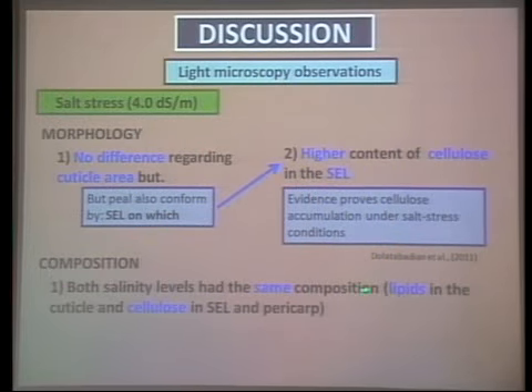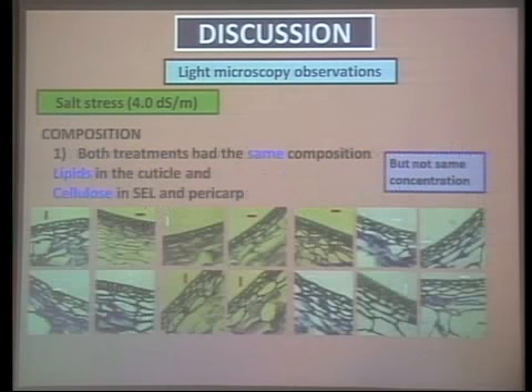In the morphology that we saw with light microscopy, we didn't see any differences in the cuticle area. But again, the peel is not just the cuticle. It's also the subepidermal layer. I presented really few pictures before, so I wanted to repeat them here. The top pictures are non-salt stress conditions, and the bottom pictures are salt stress conditions. You can see that the intensity of the cellulose here is thinner than the intensity here. There are fewer layers under non-salt stress conditions, and we have more layers with salts. So we do believe that there is a difference, not just in cellulose concentration underneath the cuticle, but that the thickness is based here.